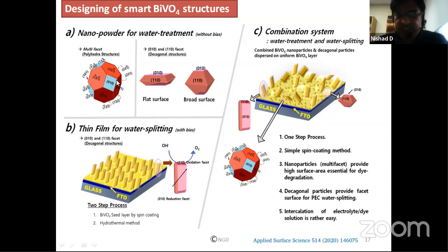So here you can see the bismuth vanadate has multiple facets. It is a polyhedra structure. Each facet is very active in bismuth vanadate. And not only that, if you go on making nanostructures, then you can control these facets, and you can make these facets like a flat surface or a broad surface where these facets are very active.